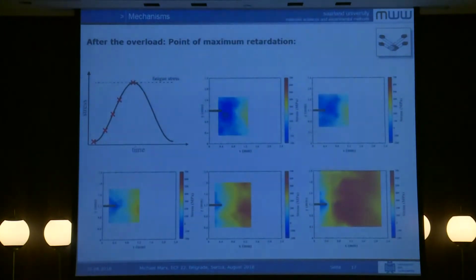And now after the overload, at the position of the maximum retardation, you have compressive stresses here. So deep dark blue means compressive stresses in front of your crack tip, and then it starts with the loading, and when you're here then you are more or less in the area where you have a more unloaded crack tip, and then the crack tip loading starts and you have your reduced loading here in front of your crack tip.